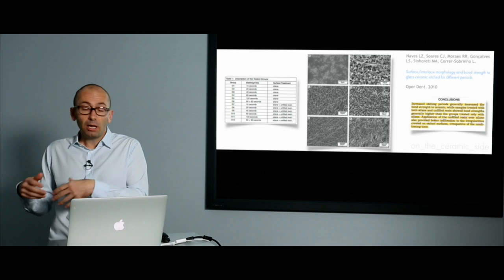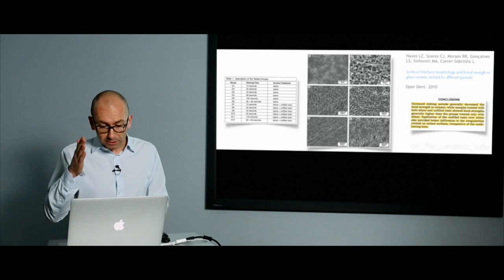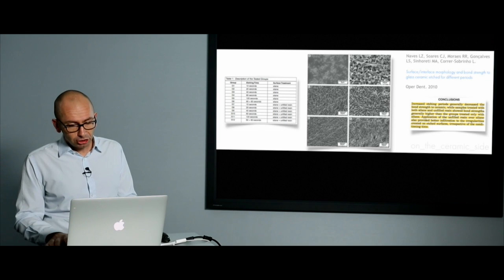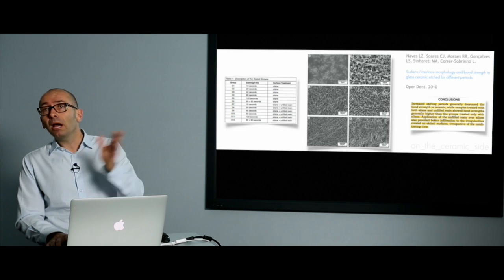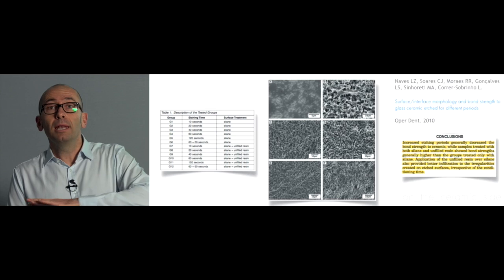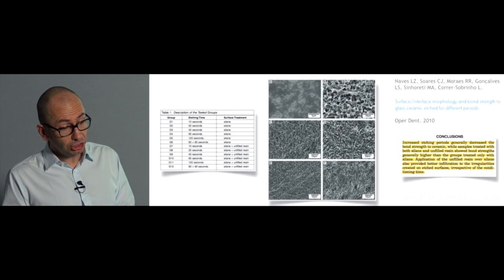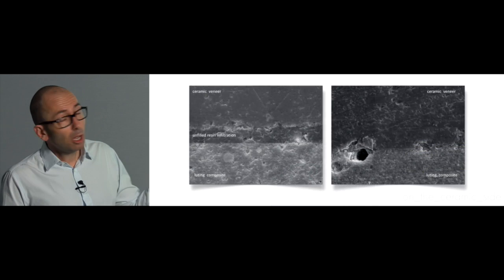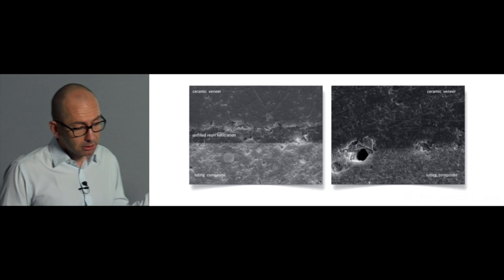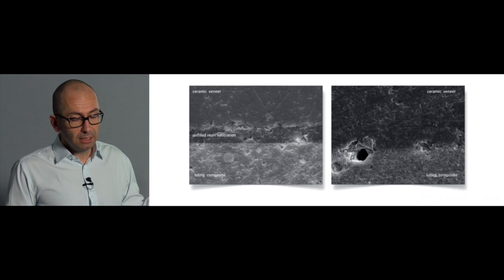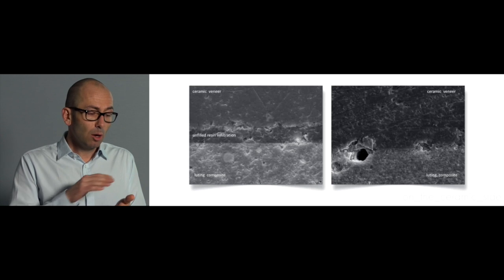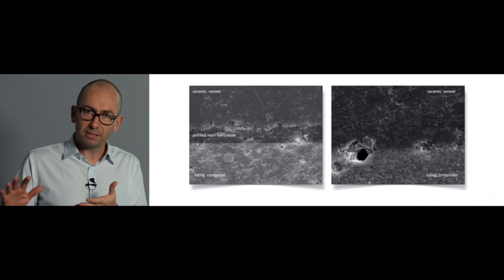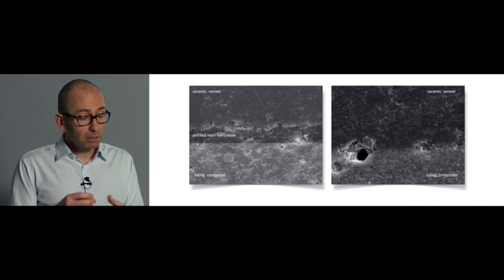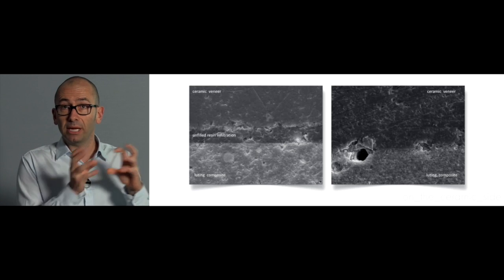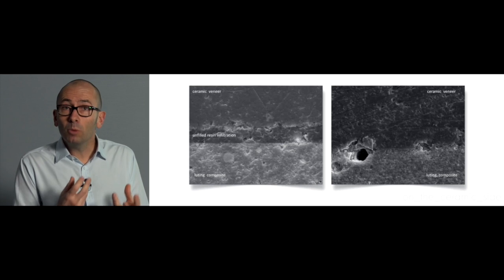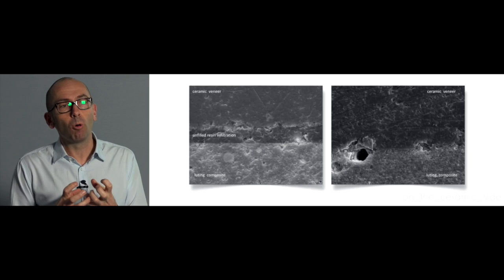So you just have to get information from the manufacturer and respect those information and recommendations very strictly. And then if we apply on top of the etched ceramic a layer of silane, it will improve the adhesion. And furthermore, if you apply on top of this, and those are scanning electron microscopy pictures, SEM pictures, you see that they covered the silane surface with a thin layer of unfilled resin, and it improves the bonding because it penetrates all the irregularities that you've created with the etching. And furthermore, it also will reinforce the ceramic.